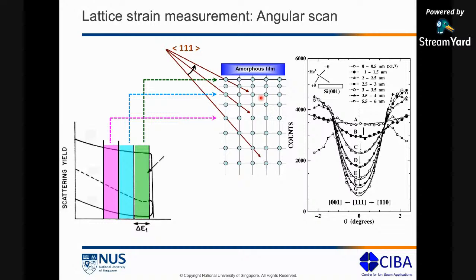higher. And if you come all the way up, all the way to A, this is even worse, right? So this has the highest counts, which means you are coming from this part of your spectrum. This part corresponds to an area which is closest to the interface, which is extremely strained, and therefore your channeling is going to be even worse, and therefore your counts are going to be even higher, right?